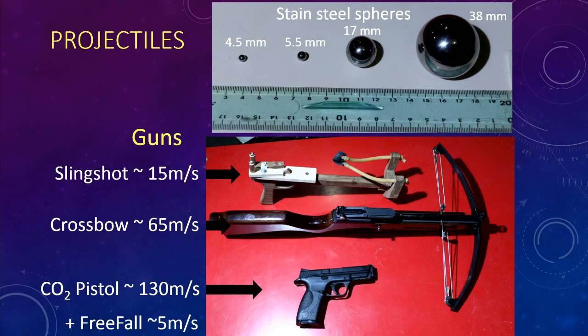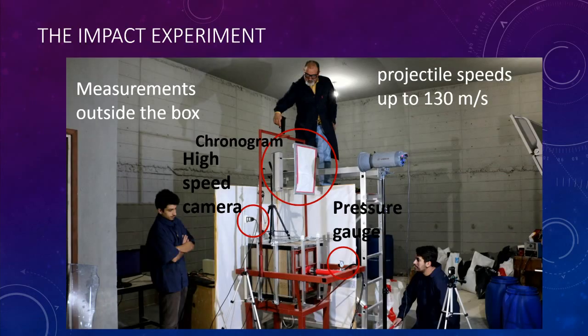The kind of projectiles that we use are usually stainless steel spheres, and at the moment we are concentrating on low speed impacts, so we use this kind of gun that allows us to have up to 130 meters per second, and also some free fall. So this is the kind of experiment that we are doing. We record the velocity with the chronograph, the impact with the high-speed camera, and the pressure with the pressure gauge.